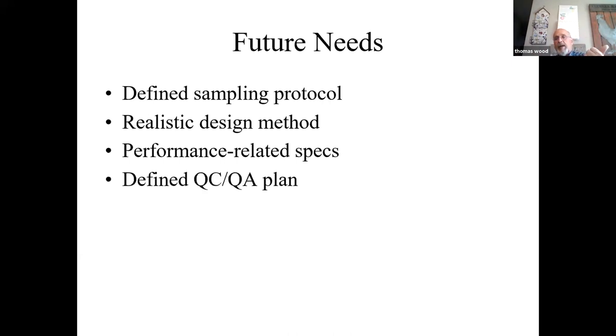A defined QC/QA plan, structural ratings, that's an area where more research needs to be done. I think MnDOT gives cold in place recycling a gravel equivalency of 1.5. I know they give that for SFDR, and based off of test sections that I've been involved with in my days at MnDOT, that's very conservative. I honestly believe that at some point somebody's going to come up with an additive package for the asphalt binder that you're going to be able to inject the proper amount into the RAP, uniformly coat it.